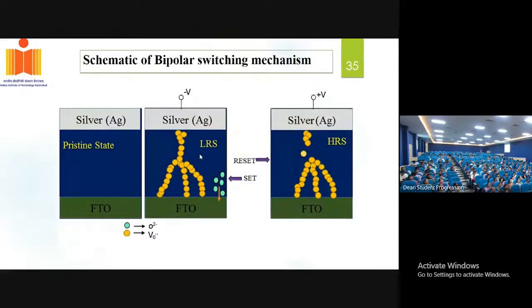As I mentioned, suppose you have a bottom electrode and a top electrode, and between them you have a dielectric material. When you apply a very high potential difference, this kind of conduction channel will form between the top electrode and the bottom electrode. This makes the device go to the low resistance state. Suppose there is a rupturing of this conducting channel, that is, the oxygen defects are not continuous, that takes your device to high resistance.